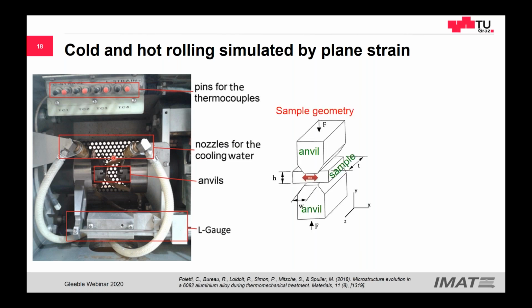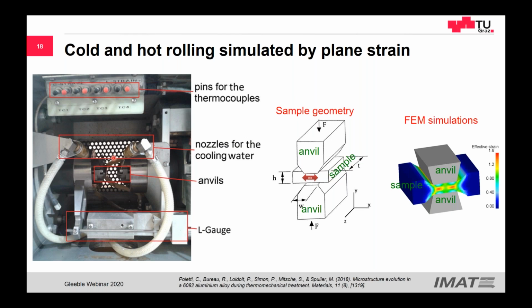So we use this sample geometry, and then we carry out finite element simulations. As you know, we usually have a gradient of temperature. This gradient of temperature is reflected as non-homogeneous deformation. You can get rid of the non-homogeneous deformation if you have a homogeneous temperature, if you just control the friction. Even if we can control the friction here, we always have a small gradient of temperature, and we produce this heterogeneous deformation.